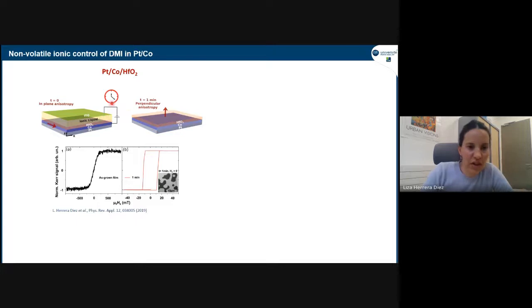So what we do here is that we apply a voltage for a given amount of time, and then we look at the magnetic state because, as I said earlier, it's non-volatile. So here you can see very well, we go from an in-plane state to a very nice perpendicular state where we can see magnetic domains. With 1 minute of applying this gate voltage.